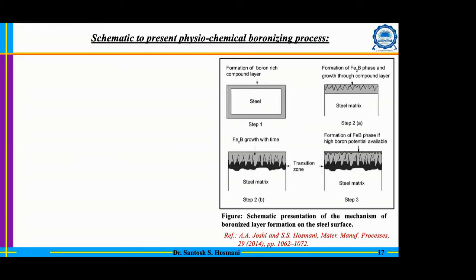And then subsequently, you can see that there is some transition zone shown here. What exactly is the transition zone? Whatever alloying elements are present in steel, all elements will not be accommodated into iron boride. Some elements have limited solubility in iron boride. Some elements do not have any solubility at all. That means they will be entirely rejected by these borides, and they will accumulate at the front of these borides, and that will form a transition zone. And many times that transition zone will alter the mechanical property, and that alteration may be disadvantageous. So that transition zone concept also we need to understand. That also we will discuss later. And then finally, you have a simultaneous growth of these three important layers: the transition zone, as well as Fe2B, and then FeB. That is what we have in the typical cross section.